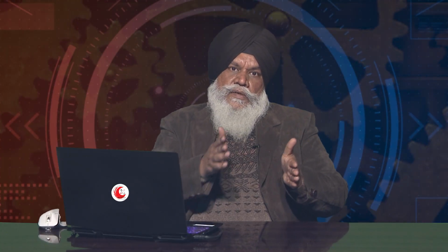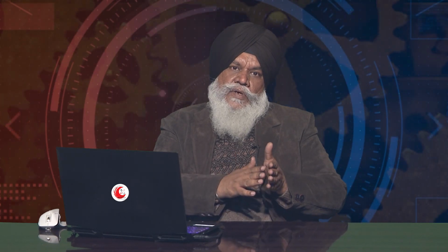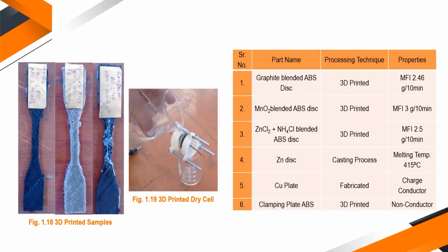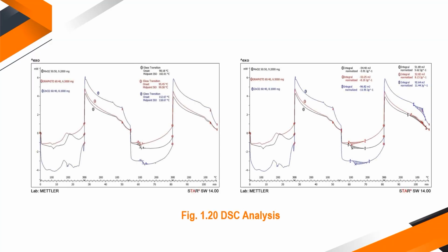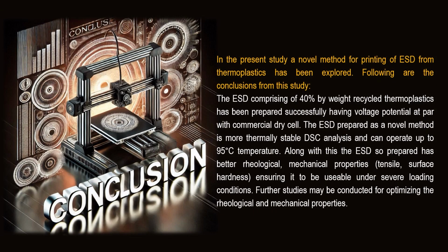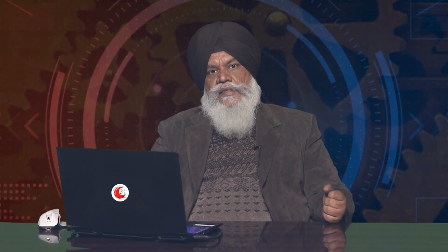So what we understood is that because of the interface of different polymeric material and the different salt, I need to excite initially for the electrons to jump across that barrier. Accordingly, we tried to make some mechanical parts and check their mechanical properties. And one beautiful thing that we learned is that this type of cell we have prepared is stable up to 95 degrees Celsius. Otherwise, our normal dry cell doesn't work above 55. Similarly, at lower temperatures, below zero, a normal dry cell doesn't work, but these were giving really good output even at -15, -10. So in low temperature areas, this can be really helpful.